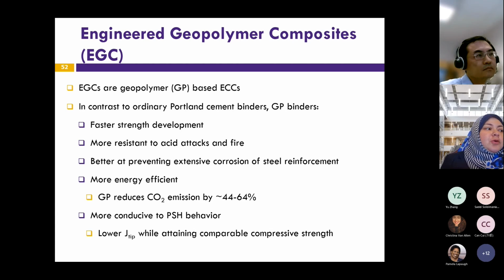All right, so as I said before, EGCs are ECC that use geopolymer instead of a cementitious matrix. Why would we do that? Because geopolymer binders have so many advantages. They have faster strength development. They are more resistant to acid attacks and fires. They also prevent the corrosion of the steel reinforcement, and using geopolymer will reduce the CO2 emissions by 44 to 64%, which makes it environmentally friendly.